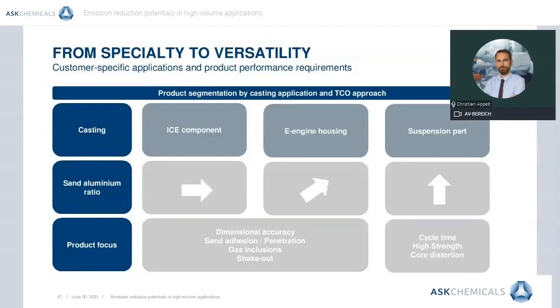The versatility of the Inotec technology is achieved by segmenting the necessary product performance requirements of the binder system by the castings produced and by considering the total cost of ownership approach that captures the full cost structure of a casting process until selling the part to the respective customer. The determining key performance indicator here is the so-called sand-aluminum ratio that compares the weight of the sand core package with the weight of the casting. The higher the KPI, the higher the sand core weight and the lower the casting weight.